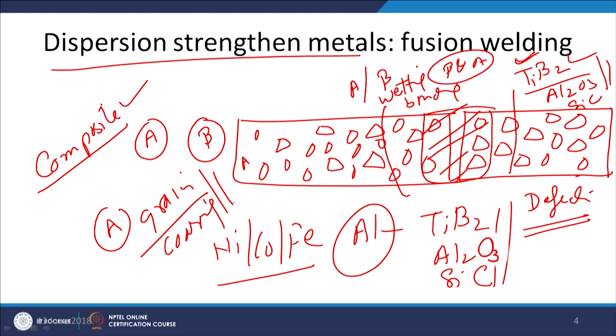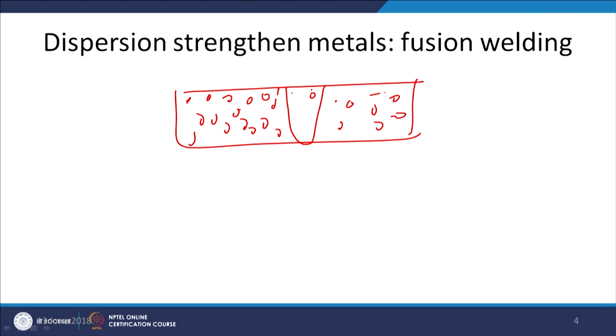So, if we try to understand the variation in the hardness in such composites subjected to fusion welding, say this is the composite material developed through the dispersion strengthening mechanism. So, here particles may be dissolved or thermally damaged, and poor bonding may lead to defective weld joints. And the heat affected zone may have coarse grain structures. So, the properties in the heat affected zone may be slightly lower, but these may be significantly lower in the weld zone because of the poor interactions between the reinforcing agent and metal matrix.